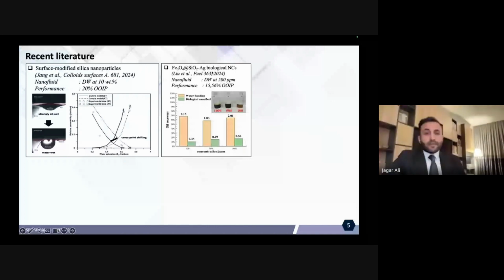So recently, we have a publication by Jang et al. about surface modified silica nanoparticles in 2024. They were able to obtain an additional 20% of original oil in place. So this is good. They reported that they obtained this improvement in the recovery factor through shifting the relative permeability.